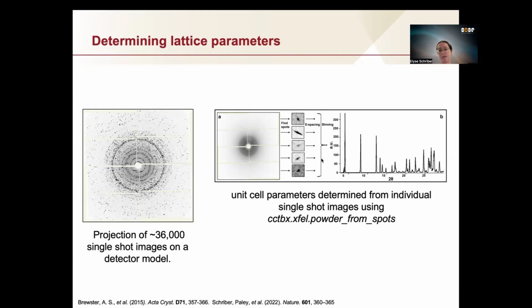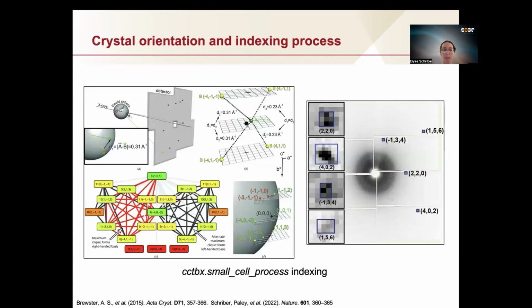And then we can bin it down to a certain size because there's a lot more pixels on the detector than we need. And we can start to form what's known as a virtual powder pattern, where we simply are using the intensities and the positioning of these spots from Spot Finder. And what that allows us to have is a powder pattern that's almost entirely free of any kind of instrument broadening. So it's very useful for now being able to get our unit cell parameters at the XFEL experiment instead of having to come with them to the experiment.